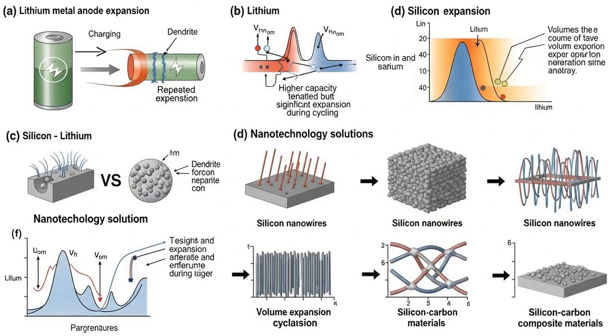So researchers are now working on making stronger electrolytes and engineering the battery's interfaces to guide the lithium to deposit smoothly. The second major issue is the volume conundrum. Lithium metal physically expands as the battery charges and contracts as it discharges. This constant flexing can cause the lithium to lose contact with the solid electrolyte, creating dead zones that no longer work and cracking the delicate solid electrolyte layer.